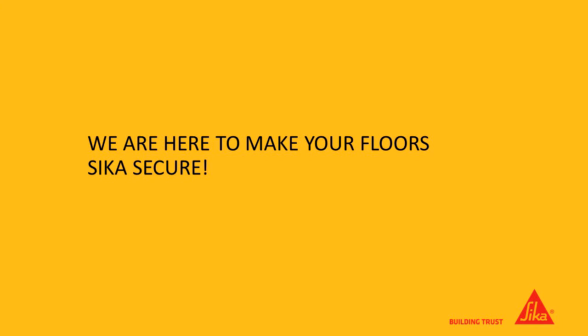You can also use any kind of pressure sensitive adhesives, for instance, carpet tile adhesive. You can go directly over top of this. The only thing it would affect is it would extend your tack time. So if your adhesive normally took a half hour to 40 minutes to tack up to be ready to put down your carpet tile, it might extend that out to about an hour because, again, that adhesive only has one direction to off gas, and that's up.